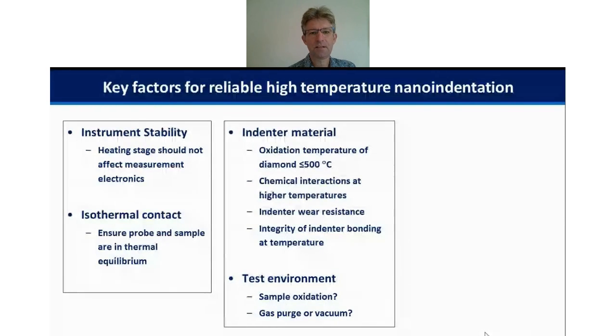The next set of things you need to worry about are around the changing chemical and mechanical properties of the indenter and sample. If you think about the hard indenter material itself, which typically is diamond at room temperature, well, diamond works really well at high temperature testing up to about 450, maybe 500 degrees, and then it oxidizes in air, and that puts a pretty hard limit on using diamond above those temperatures. It just effectively burns away. You also need to think about chemical reactions between the tip and the sample at high temperatures that may not occur at room temperature, and you need to bear that in mind with your indenter choice.